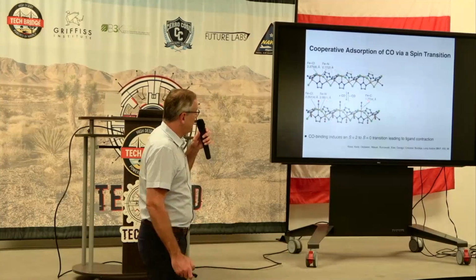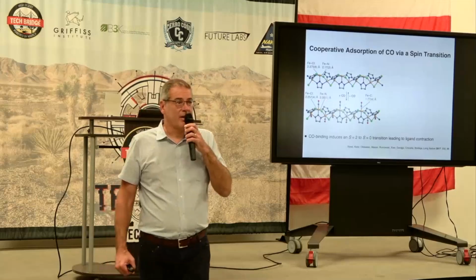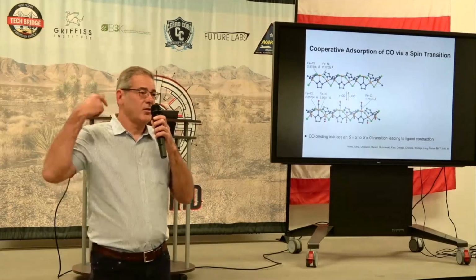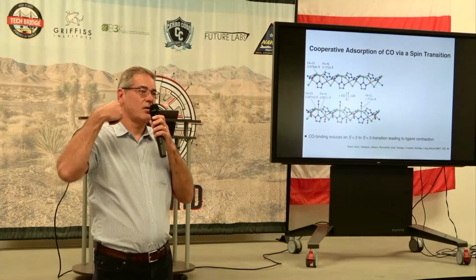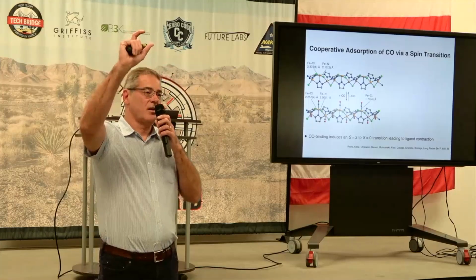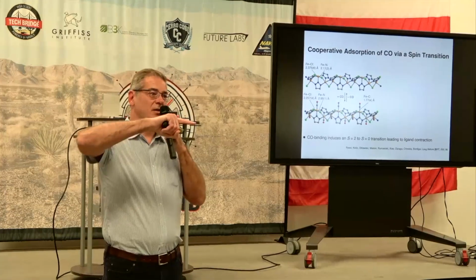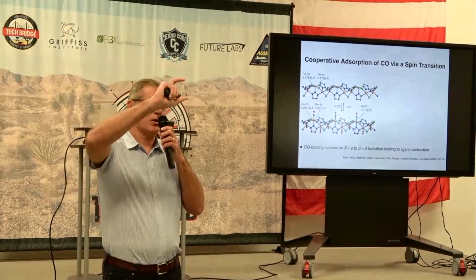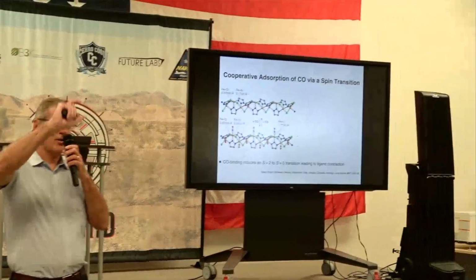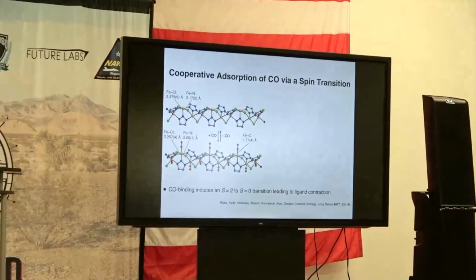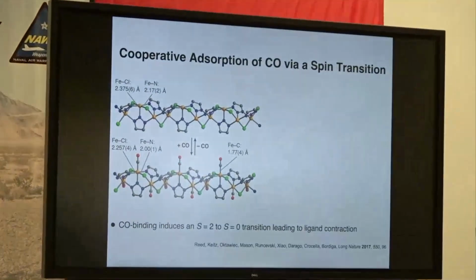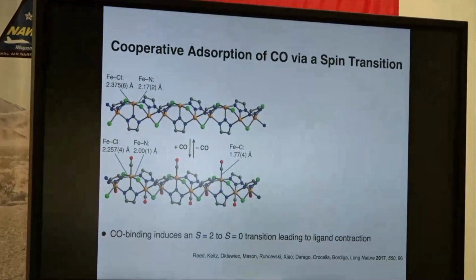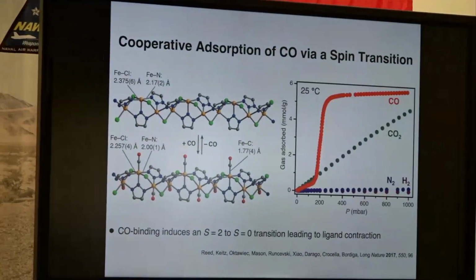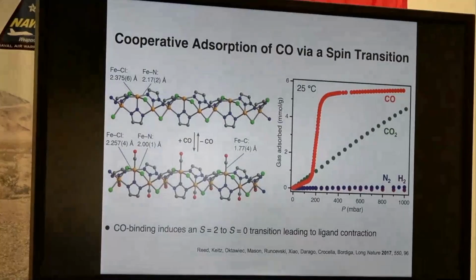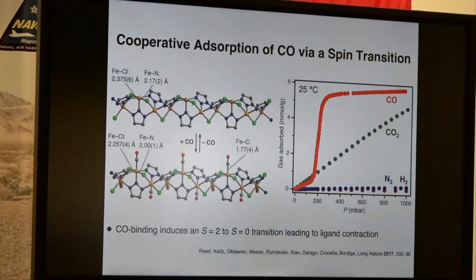And so we took advantage of that and designed a MOF, again a honeycomb type MOF, that has rows of iron 2 centers with an open coordination site. And the iron 2 is high spin, but when it binds CO, it goes low spin. And that spin transition is selective for CO. Other molecules aren't strong enough field ligand to drive the iron low spin. And so here's the first nice step for carbon monoxide adsorption under these kinds of conditions.